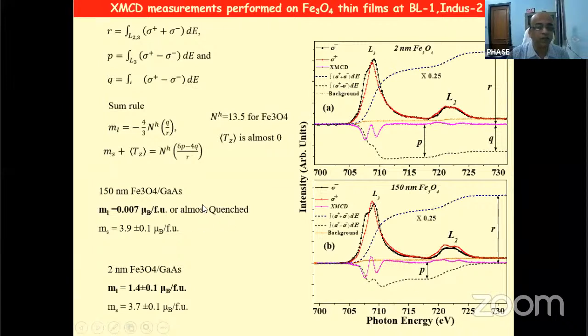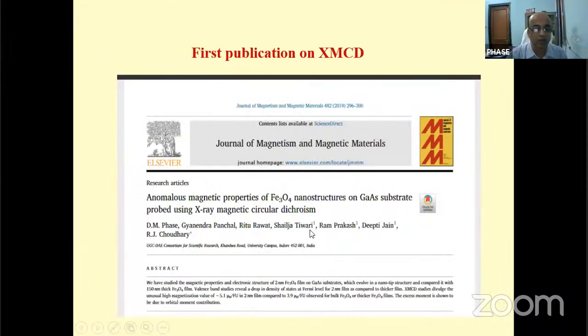Normally in a three-dimensional structure, the orbital moment is quenched. And in this 2 nanometer Fe3O4, you can see that a 1.4 orbital moment is there. So the material is the same Fe3O4, but in nanometer form, the magnetic moment is higher. Normally one would expect that the 150 nanometer thicker film should show the higher magnetic moment, but the 2 nanometer sample is giving the higher magnetic moment. So these are the conclusions, and this is the first paper from our country on XMCD.